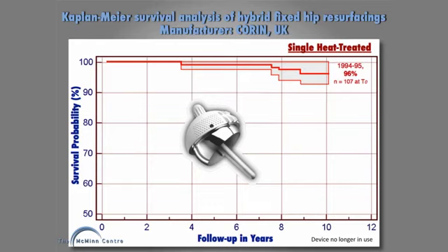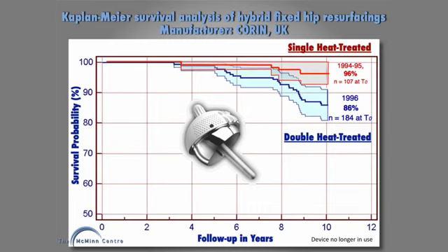I then started to develop some confidence in the method and increased my numbers. And unfortunately, as the company who manufactured these devices had to increase the numbers, they found that they were getting too high a scrap rate for microporosity in the metal, and they decided to double heat treat with hot isostatic pressing and solution heat treatment the components. And I was unaware of this at the time, but it turns out that that double heat treatment led to a deterioration in the outcome, and that series, unfortunately, with double heat treatment has an 86% implant survival at 10 years, and unfortunately those implants continue to deteriorate and fail.